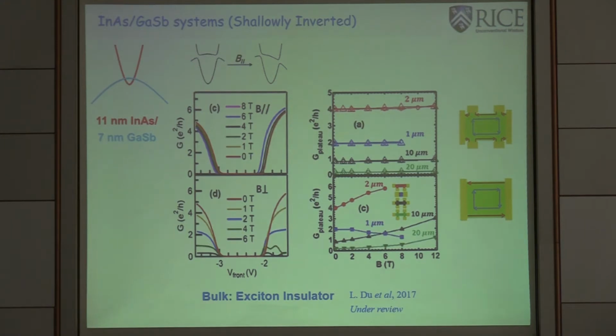Okay, so what might be the reason? One of the reasons is that this picture is based on tunneling between electron and hole layers. If there's no tunneling, of course, this will not happen. Therefore, we guess that in the very low density region, the tunneling somehow is suppressed, and therefore this single-particle hybridization gap does not occur. Okay. Of course, one scenario is that tunneling at such a low density is overwhelmed by the electron attraction between the electrons and holes. Therefore, these electrons and holes form pairs. They are fixed in each quantum well. So that gives a scenario of an exciton insulator.